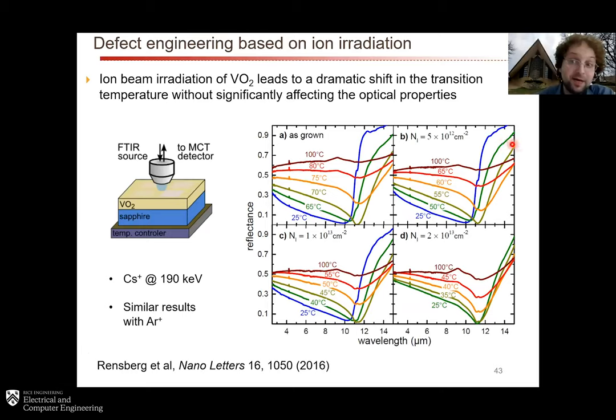We've done a lot of materials work as well. This is just an advertisement of a paper from a few years ago where we found an interesting way that we can engineer the phase transition temperature of VO2 after the fact, so not during growth, but after the fact using focused ion beam by doing defect engineering and essentially changing the transition from 70 degrees all the way down to 25 degrees. And this is, of course, quite useful for thermal emission engineering applications.